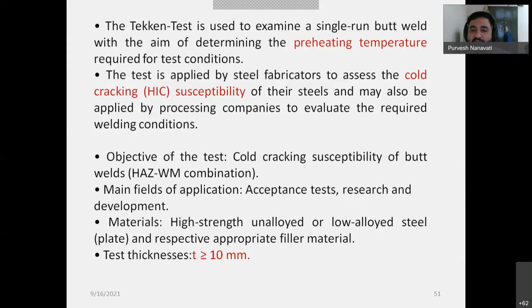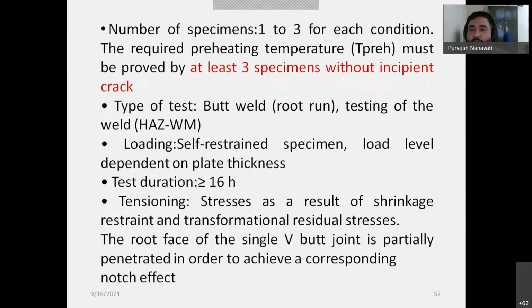So this is the objective of the test, and for the number of test coupons, you can go for 1, 2, 3 for each condition, and you can decide the preheat temperature. You first start with some 25 degrees Celsius, 30 degrees Celsius, and you go on taking different preheats, checking out the possibility. But the test duration is more than 16 hours, right? Because you have to see the cold cracking, you have to examine the cold cracking susceptibility. So you have to wait up to 16 hours to observe the test coupon for the development of a crack, right?